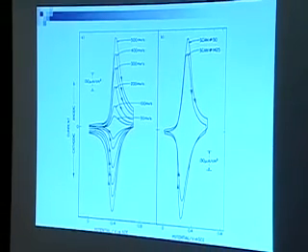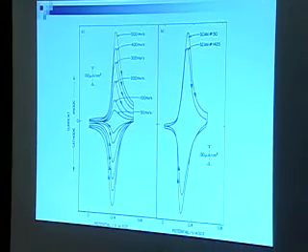I can take cyclic voltammograms of the system, nickel ferricyanide on nickel. First, we just did a whole bunch of them. There's scan 1425 versus scan 50, to show at 100 millivolts a second that it's a pretty stable system. A nickel electrode itself lasts for about 10 scans. And by that point, it's got so much oxide on the surface that it's passivated. No current can flow. We have a little drop-off after 1,400 scans, but it's not bad. We have stabilized the system, practically speaking.